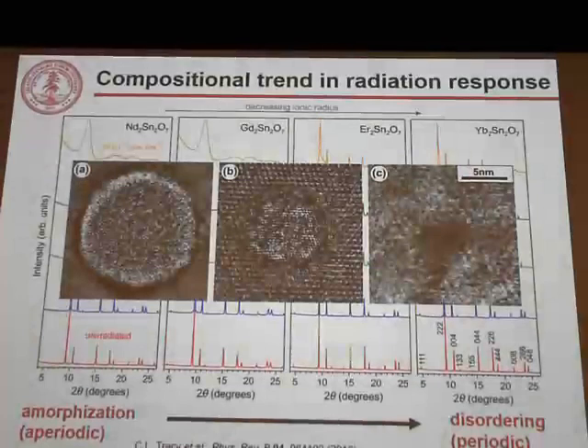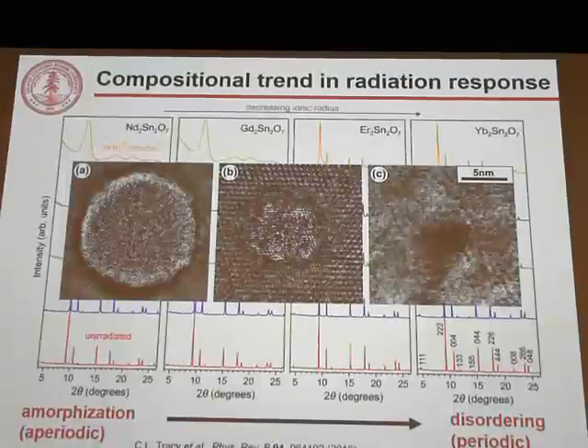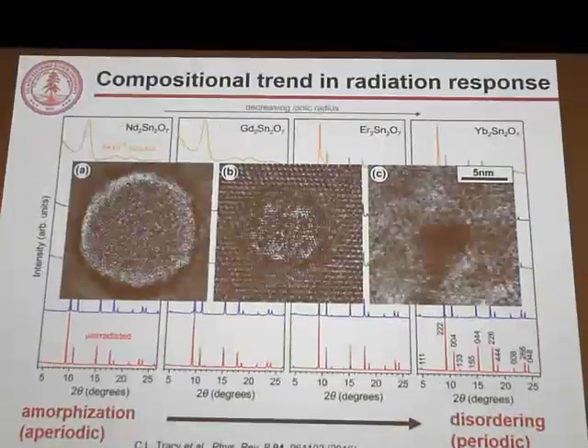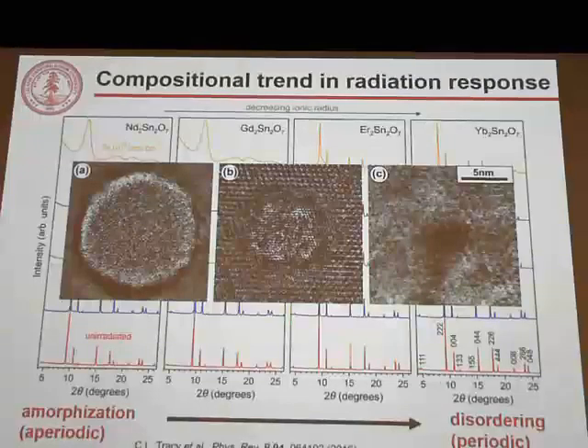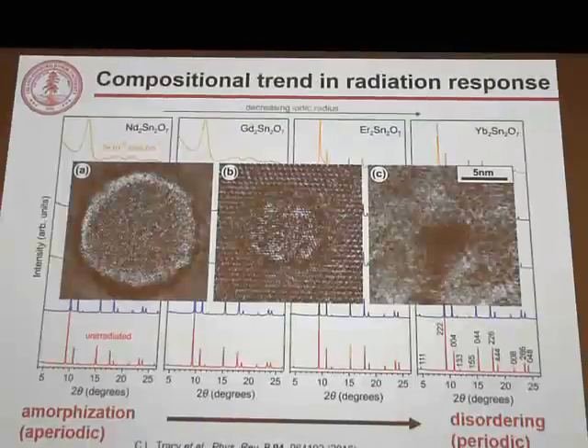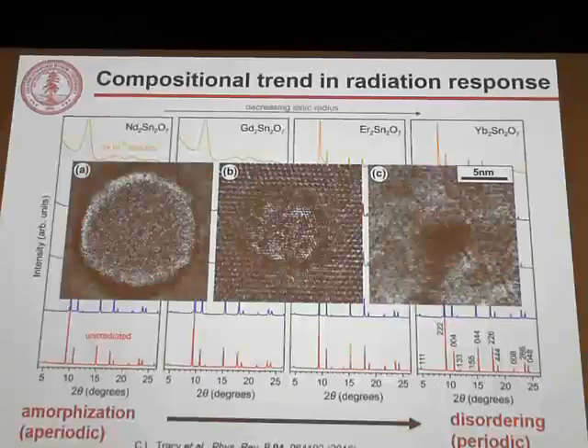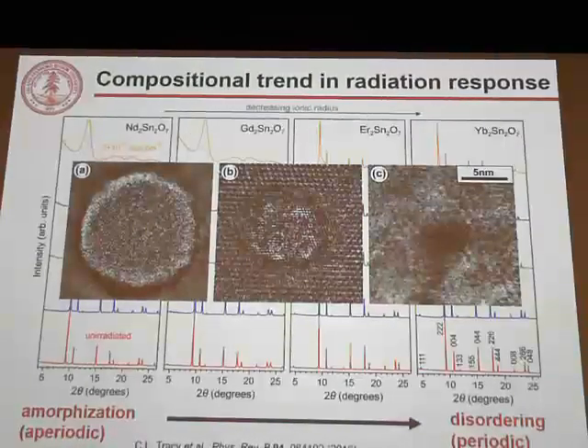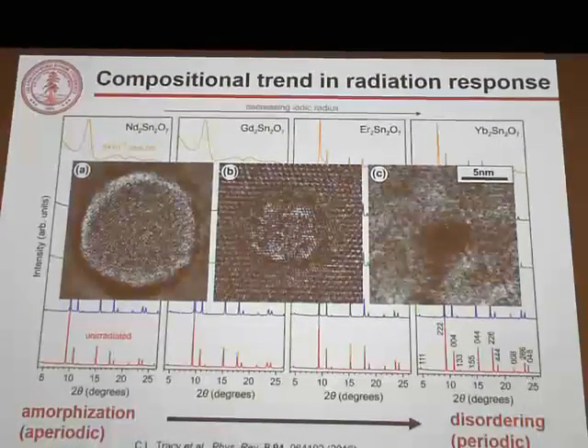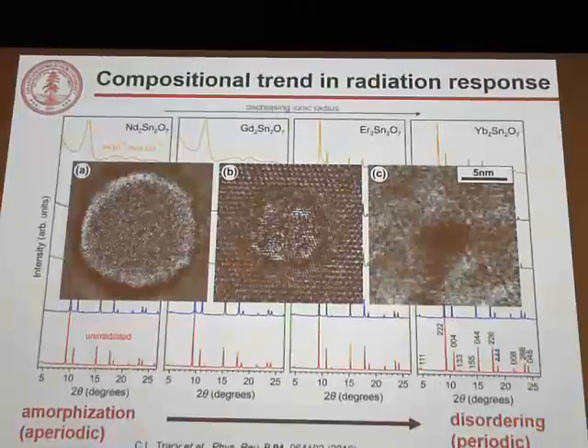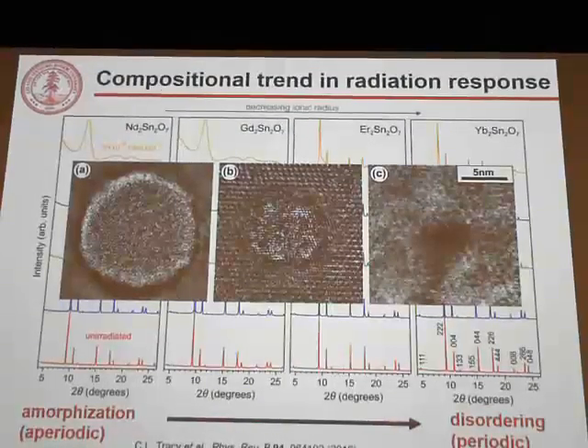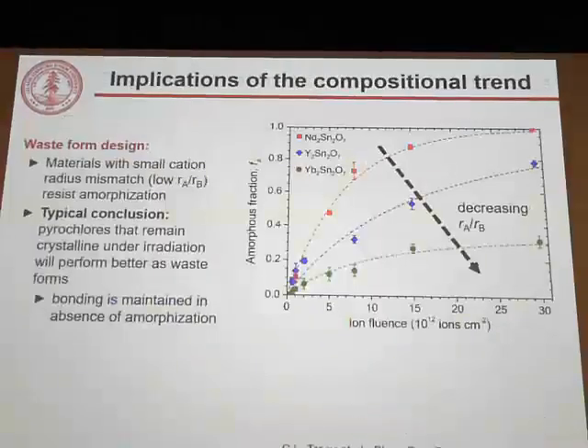So I show here TEM micrographs of ion tracks in these different materials, the results of irradiation with a single ion. And you see for materials like neodymium stannate on the left, we have these large amorphous regions that are induced by irradiation. Under the same irradiation conditions on the right, ytterbium stannate shows very little damage, just some contrast, probably due to a few point defects in there.